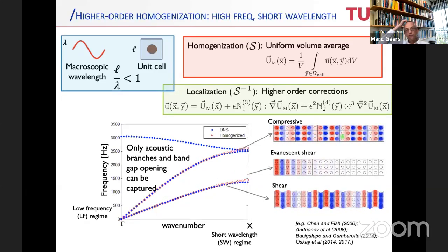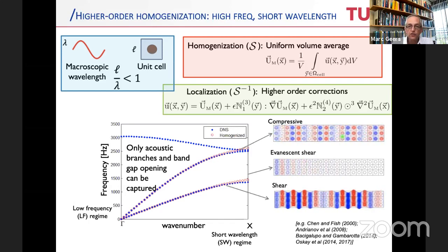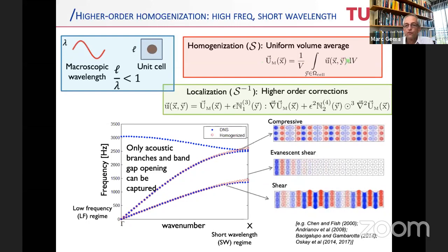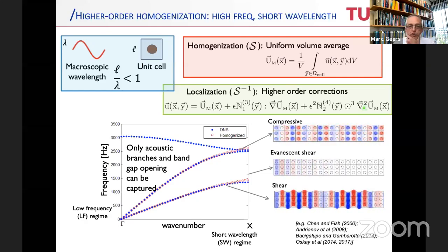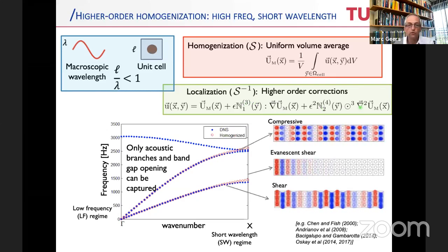I could go one step further, which is relevant for high frequency, short wavelengths, still having a homogenization operator that is the uniform volume average, but now clearly a higher order asymptotic expansion. That has been done in the literature. I know that Jacob also contributed a lot to this, and it works already fairly well because it already picks up the acoustic branches of the problem. So only the higher order correction already has a clear contribution to improving the solution.